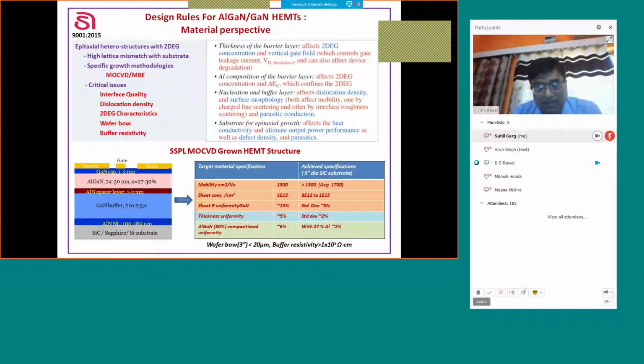So depending on the requirement, we have to fix up the thickness of our barrier layer, and then the aluminum concentration also decides the band gap, and it then gives you the conduction band discontinuity, which is very important for the confinement of the carriers. So to have high sheet carrier density in the quantum well, we have to have high thickness as well as high aluminum concentration. But to have high thickness or high aluminum concentration has other consequences. So we have to have a compromise. We just cannot increase thickness or increase aluminum concentration, because the growth issues become difficult, and we have to have a very good interface quality.